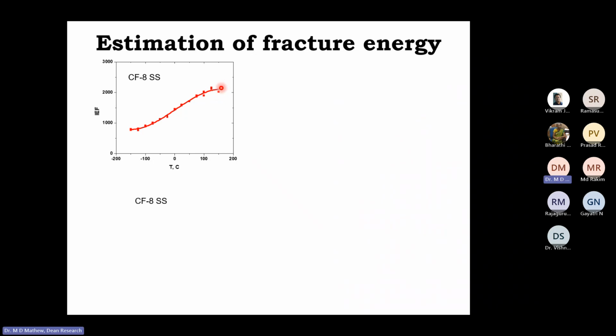You find that at higher temperature, IEF values tend to be constant. But as you decrease the temperature, it continuously decreases. And then again, it reaches a constant value at temperatures less than minus 100 degrees centigrade. So you would imagine that this is a ductile to brittle transition curve, like the one you will generate in a conventional impact test.